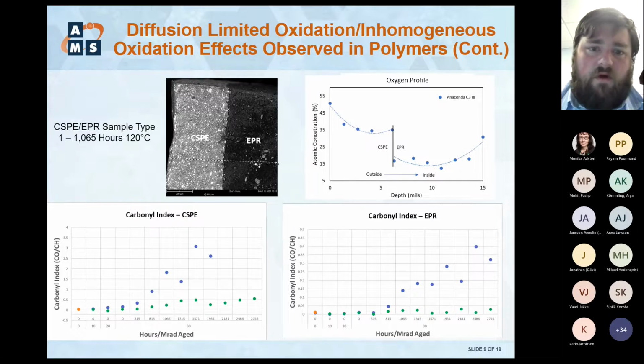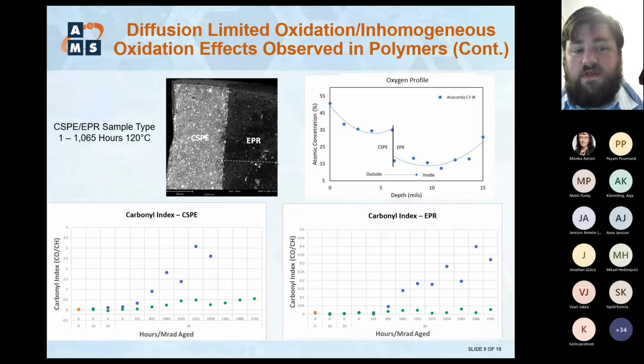You can see the oxygen profile from the EDS scan. This is data taken at 120 degrees C after 1,065 hours of aging. You can see the oxygen profile, the differences in the levels of oxidation and the oxygen profiles in the two different materials in this insulation. You see the Hypalon has much higher. So again, in this case, the EPR we've noticed is very affected because of the DLO effects we see.